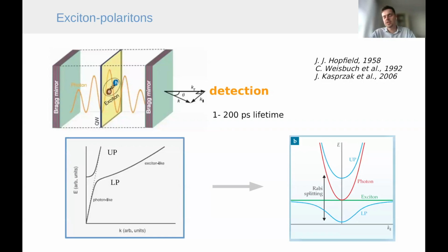Another way, actually, the range of possibilities is much wider in semiconductors because, for example, we can introduce additional quantum wells with electronic gas, and then we can create so-called polarons, which have much stronger nonlinearity than just plain polaritons. We can also use an electric field to create dipolar polaritons, and they also have much stronger nonlinearity.